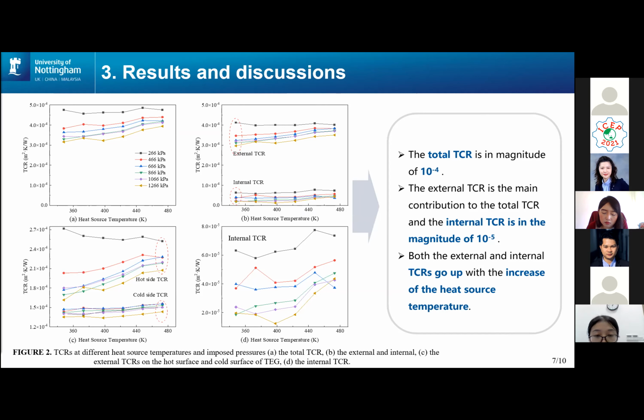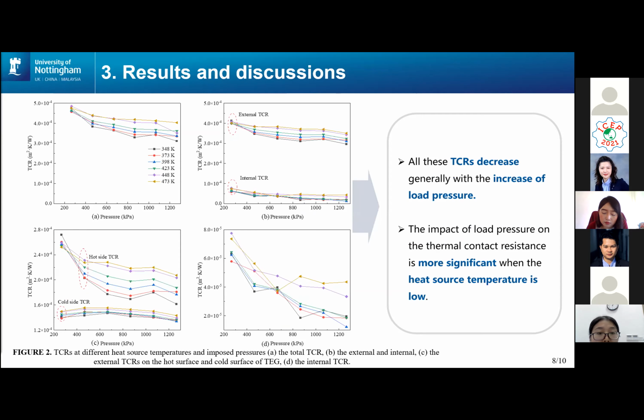The charts on the bottom respectively give detailed information on the TCRs on the hot side and cold side and the internal TCR. It can be concluded that both the external and internal TCRs go up with the increase of heat source temperature. The 4 charts here show the influence of load pressure on the thermal contact resistances. From the results, we can see that all the TCRs decrease generally with the increase of load pressure. The impact of load pressure on the TCR is more significant when the heat source temperature is low.